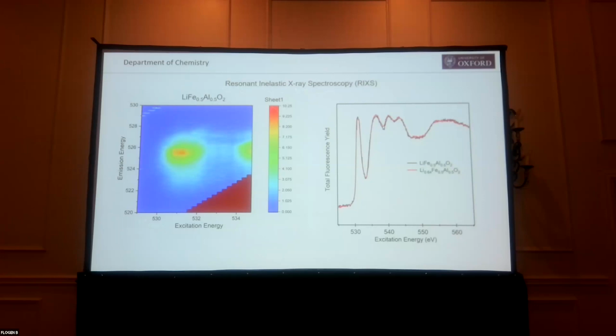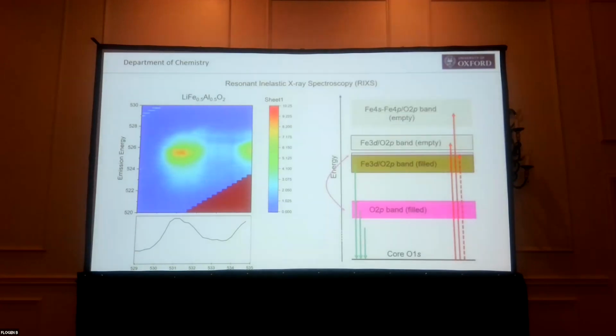So now I'm showing you excitation energy on this axis, as we have it here. But now, rather than total fluorescence here, we've got the emission energy here, and that's the contour color, so the number of photons. So we can take this data and we can just integrate it. I can integrate over these columns of excitation energy and recreate my spectrum. But from what I said before, I'm expecting to see some low energy or lower energy emission from the oxygen. So I should see an enhancement in emission here after oxidation.